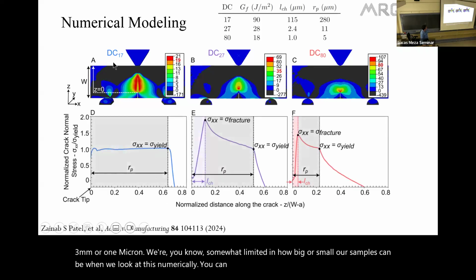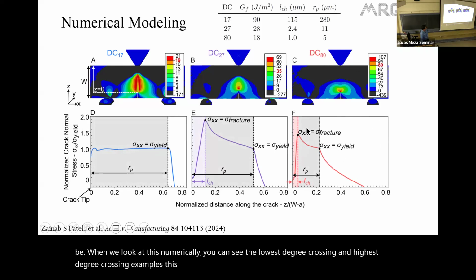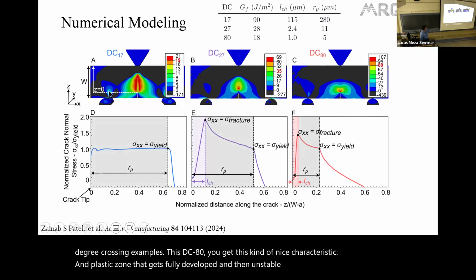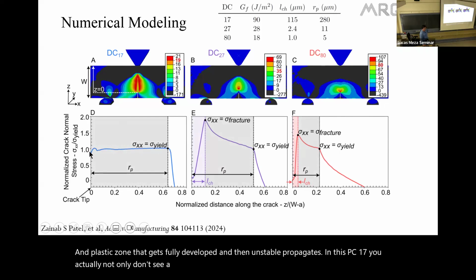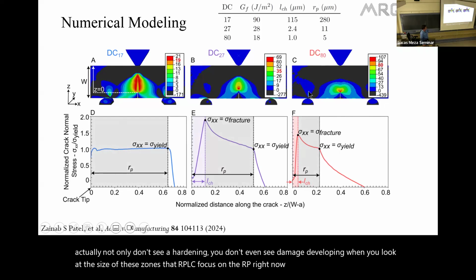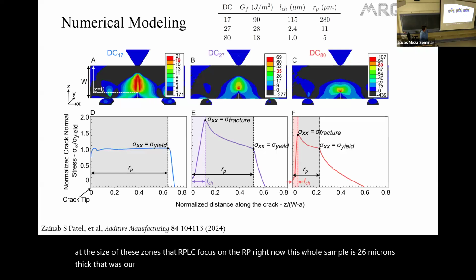When we look at this numerically, you can see the lowest degree of cross-linking and the highest degree of cross-linking samples. This DC80, you get this kind of nice characteristic damage and plastic zone that gets fully developed and then unstably propagates. In this DC17, you actually not only don't see a hardening, you don't even see damage developing. When you look at the size of these zones now, that RP, LC, focus on the RP right now, this whole sample is 26 microns thick.